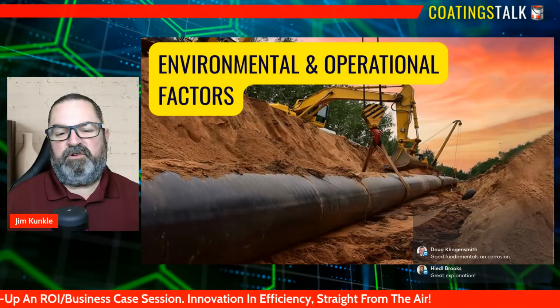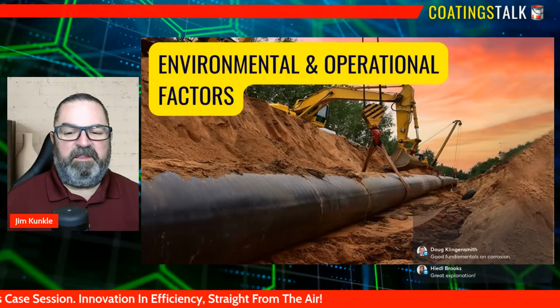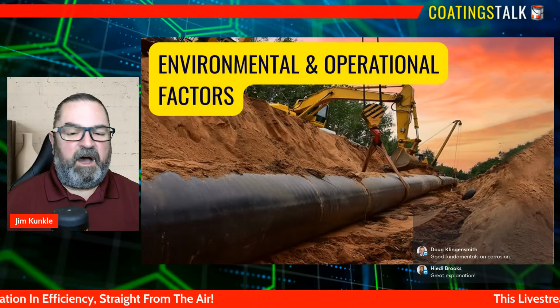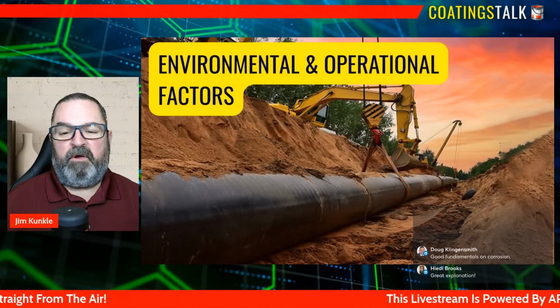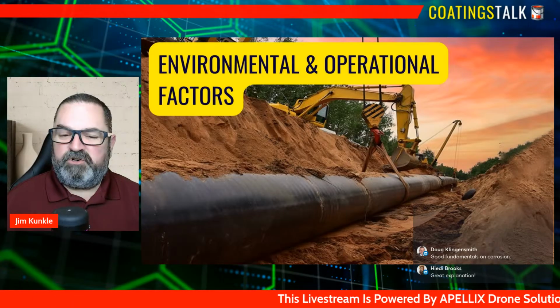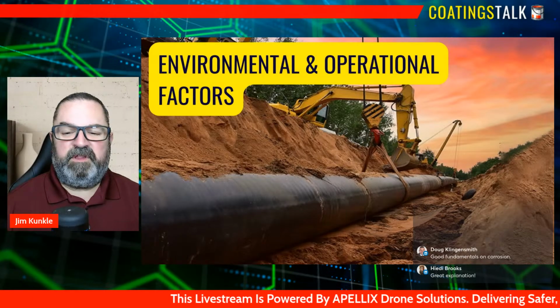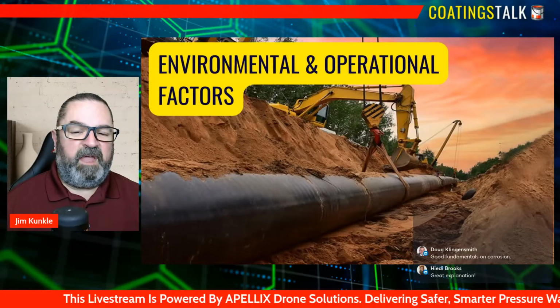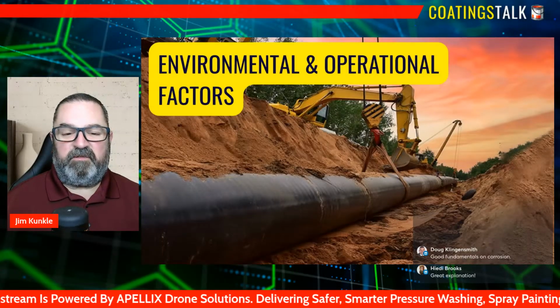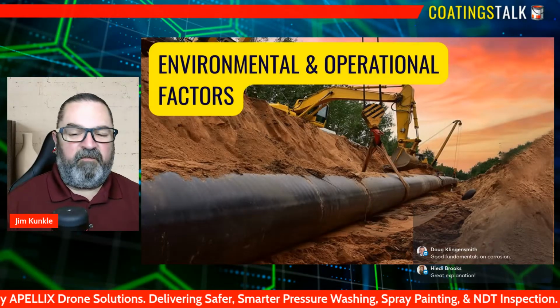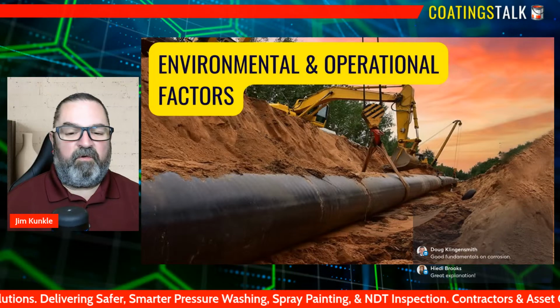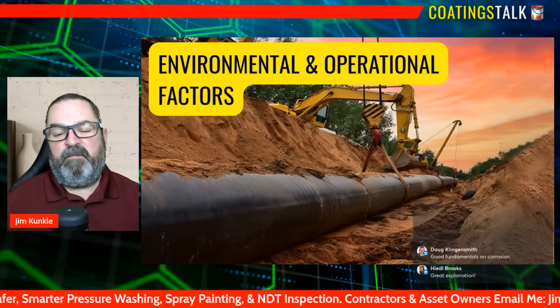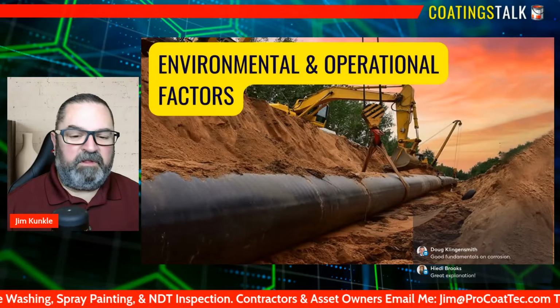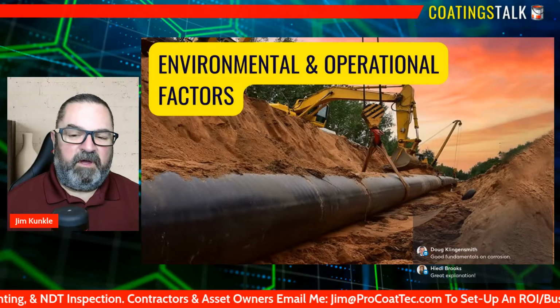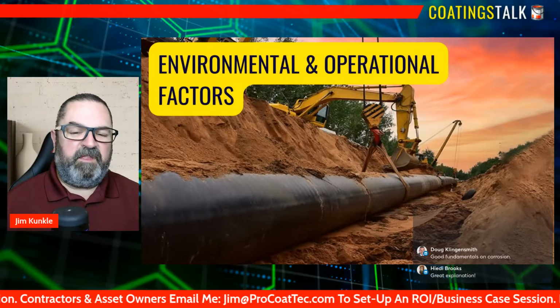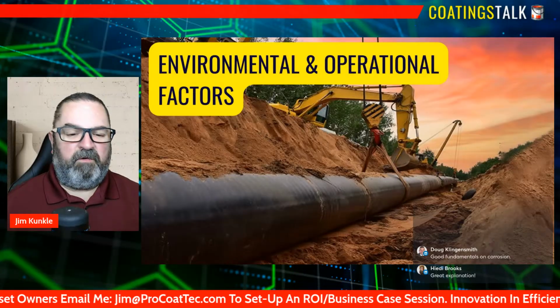Even when surfaces look dry, moisture in the air can condense in shaded areas, under insulation, or on cool metal during temperature swings. Temperature plays a dual role. Warmer conditions speed up chemical reactions, while rapid temperature changes cause condensation cycles that repeatedly wet and dry the surface. Each cycle restarts the corrosion process and accelerates metal loss over time. Salt is one of the most aggressive accelerators of corrosion because it dramatically increases the conductivity of the moisture on the metal surface.